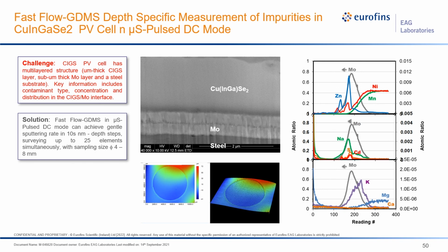The second example we're dealing with here is, again, using fast flow GDMS, but for depth-specific measurement of impurities in a CIGS photovoltaic cell. We're using microsecond pulse DC mode. One of the challenges in a CIGS PV cell is that it has a multi-layer structure. It has a micron thick CIGS layer, a sub-micron thick moly layer, and a steel substrate. The key information includes contaminant type, because you need to know, and the concentration and the distribution, particularly in this interface.